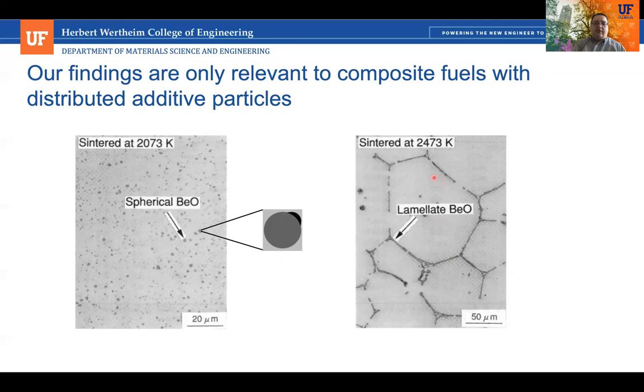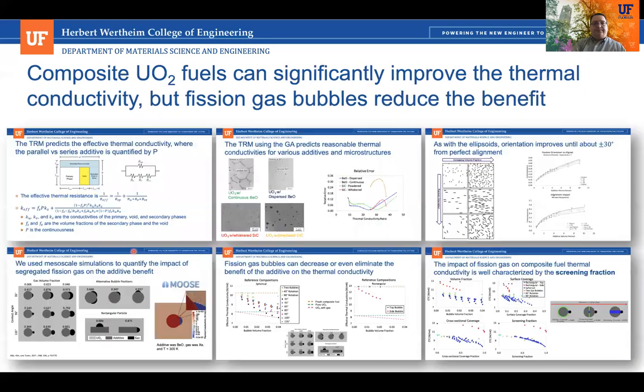And I suspect that they're going to be less impacted by the bubbles, because even if we have a lot of bubbles on either side of this additive, we still have a continuous path for the heat transport to move through along those grain boundaries. And so I suspect, again, we still need to look into this, that it's going to be more resistant to the impact of fission gas than these dispersed particles.